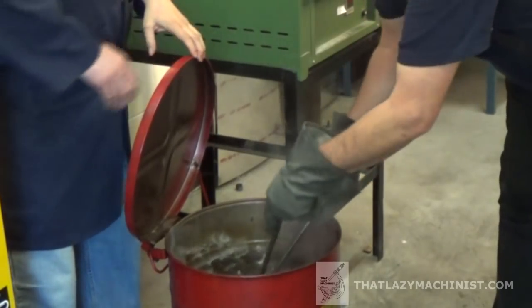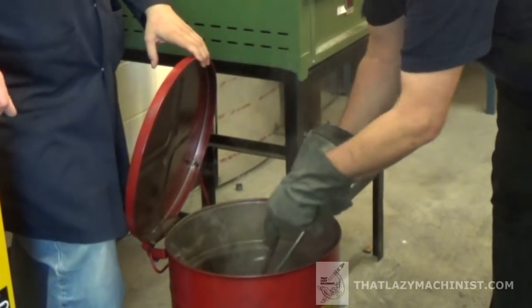Now, the last thing that I often get questions about the quenching itself, well, is why once we quench do we move around? Now, when you dunk your part in the large quantity, you don't do this in just a little bit. You need a big barrel or a large container. We're talking several gallons here. When we dunk it in there to quench the part, oftentimes you'll see me moving in a slow figure 8 movement so that the part moves around in the oil. I never pull it out until it's cool enough not to ignite, so somewhere below 600 degrees, but I will move it around. Now, why is that?